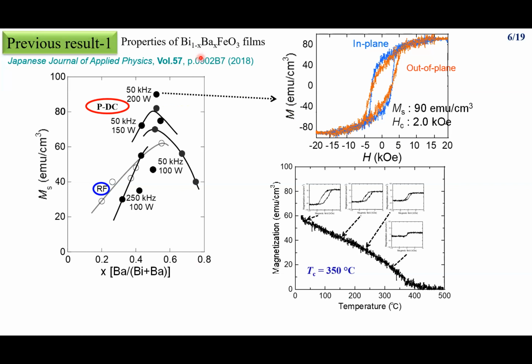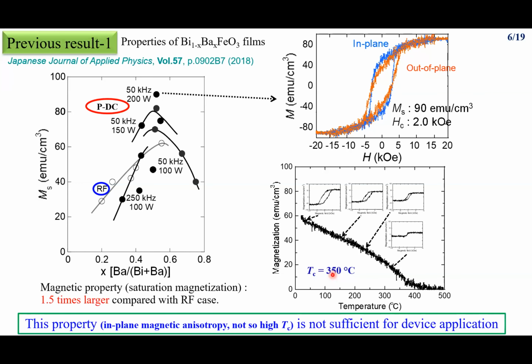In our first trial, we substituted barium and we could enhance the magnetic property. As I said, the pulse DC could increase the magnetic property. So this is very clear: in the case of pulse DC, we could increase the magnetic property at a concentration of 40 to 60 atomic percent, and this is the signature of the enhanced magnetic property. But here again, there are two problems: the Curie temperature is not so high, and this showed in-plane magnetic anisotropy. As I said, I need perpendicular magnetic anisotropy.